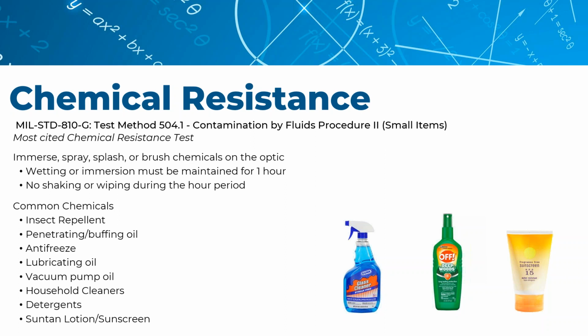So MIL 810G is going to show some different ways. It's test method 504.1, where you're basically taking the chemical and applying it to the optic just as it would be in the real world. If it's completely immersed, then you're going to immerse it. If it's with a spray, you make sure it's sprayed over the entire surface. You don't shake it, you don't wipe it dry, and you leave it for an hour. After that, you slowly dry it and you check the surface for any visible damage.